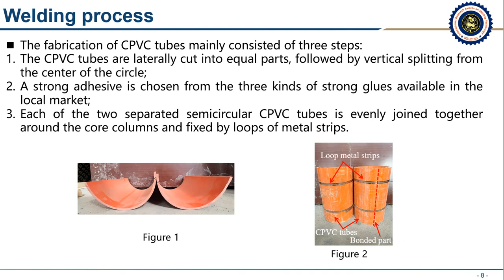Each of the 2 separated semicircle CPVC tubes were evenly jointed together around the core columns and fixed by loops of metal strips. After the adhesive is cured, loops of metal strips are installed. Fig 1 and Fig 2 separately show the relative jointing process on the bonded CPVC tubes. The bonding joint exhibits almost the same properties as CPVC tube through an actual falling test. Based on the welding processes, they can be applied in strengthening columns.